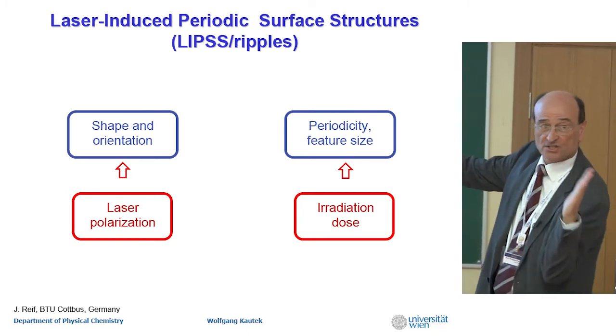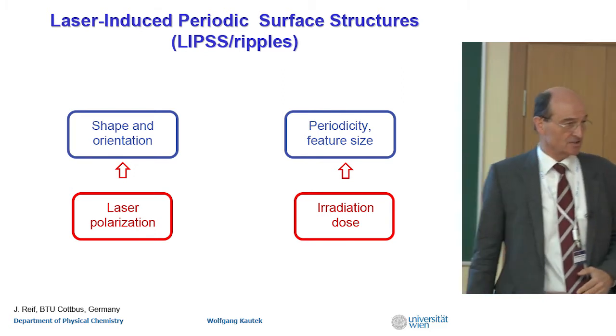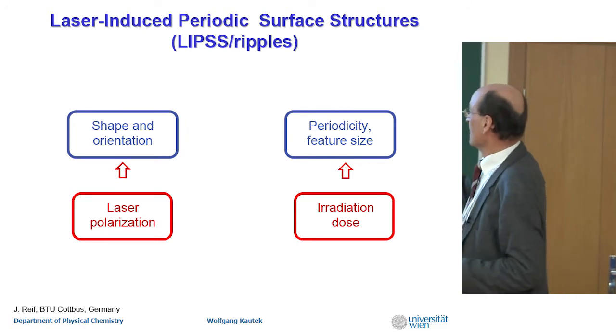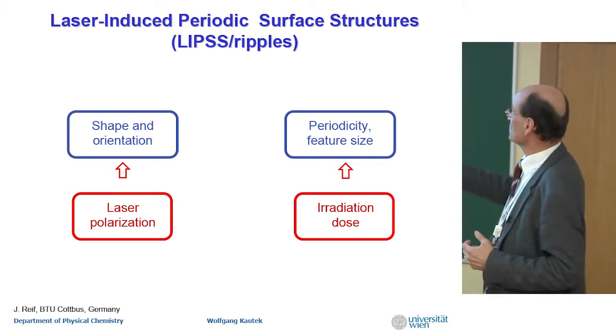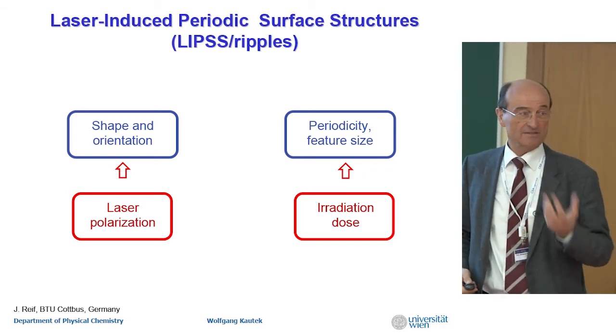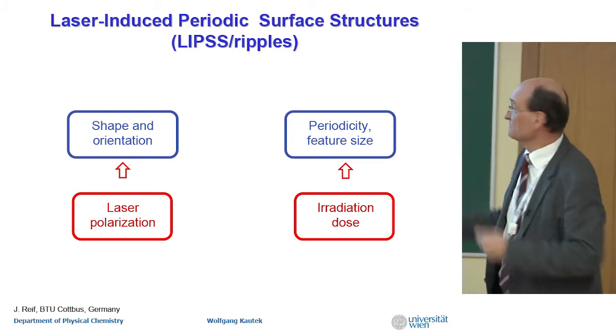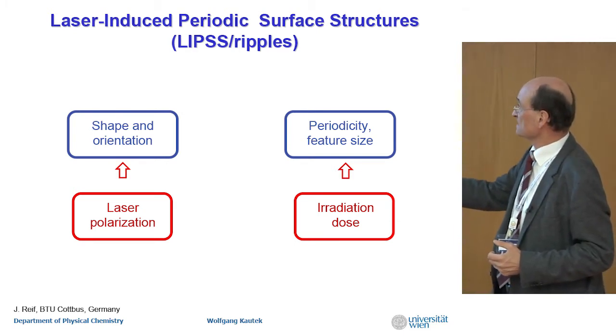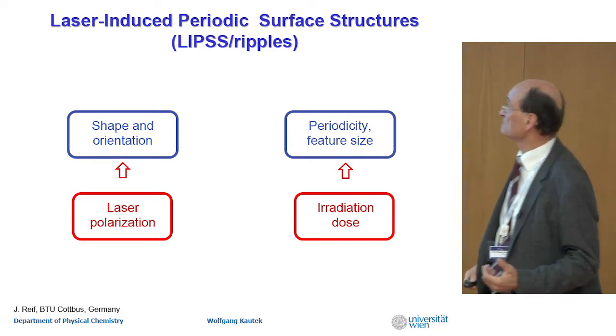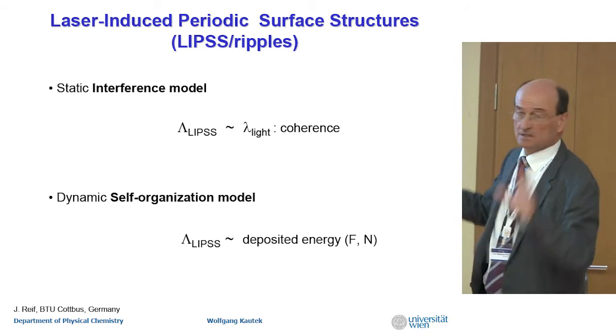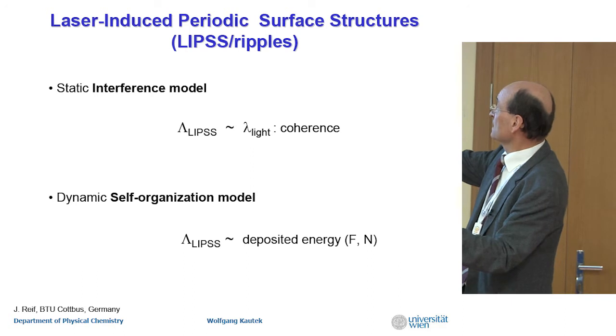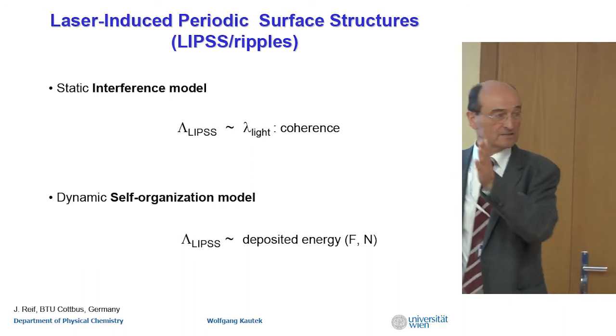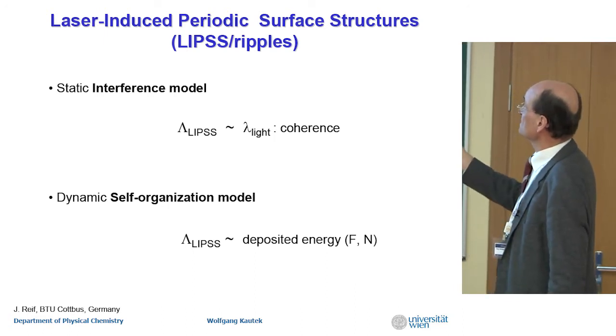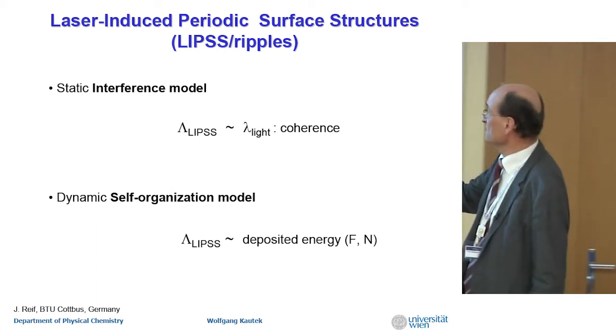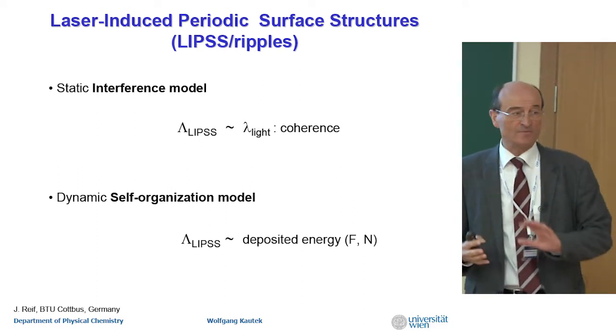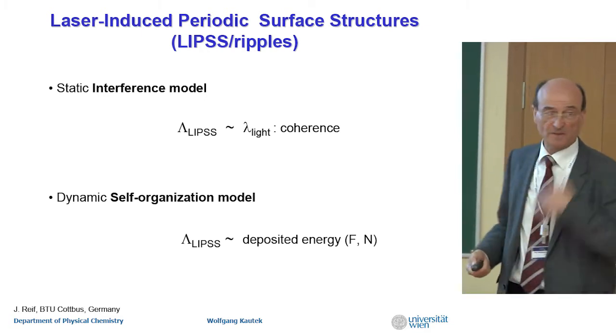The shape and orientation is controlled, as I told you, by the polarization. It's a very miraculous thing still. And the irradiation dose, the energy density, controls the periodicity, interestingly, and the feature size. Okay? Remember, we already had the picture. We are looking at this here. So self-organization has to be understood. In the static interference model, classical, the periodicity, capital Lambda, is proportional to the wavelength of the light, you know. Classical optics. Coherence is necessary. In the dynamic self-organization model, the periodicity depends on the deposited energy and the number of pulses.